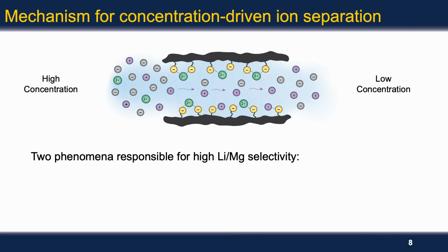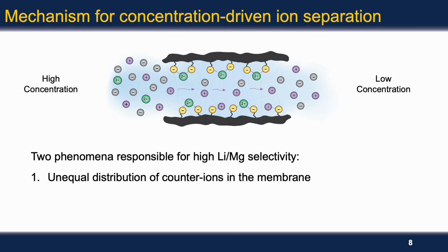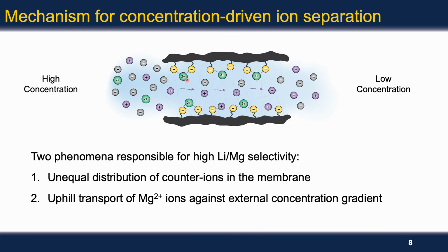In the next few slides, I'll show that there are two key phenomena that are responsible for the high lithium-magnesium selectivity that we observed during concentration gradient-driven transport. First, there's an unequal distribution of counterions within the membrane. The coions that are responsible for concentration gradient-driven transport are primarily balanced by lithium counterions. It turns out that the magnesium counterions prefer to balance the fixed charge groups along the polymer backbone, and so they cannot exit the membrane unless replaced with another ion. Secondly, we saw that there's likely uphill transport happening for magnesium ions, so they can transport from the low concentration side to the high concentration side under certain conditions, and these two effects combine to give the exceptional lithium-magnesium selectivity that we observed earlier.